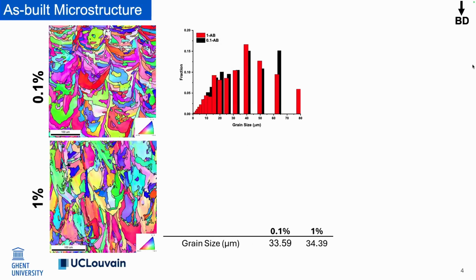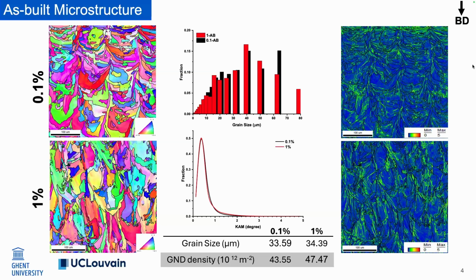The initial microstructure of those batches is quite similar, with close grain size and grain size distribution, and we have elongated grains along the building direction. KAM map and KAM intensity distribution also show that dislocation density is very close in those batches, and we can infer that if there is a significant difference between hydrogen embrittlement of these two batches, that should be because of porosity presence and not microstructure.